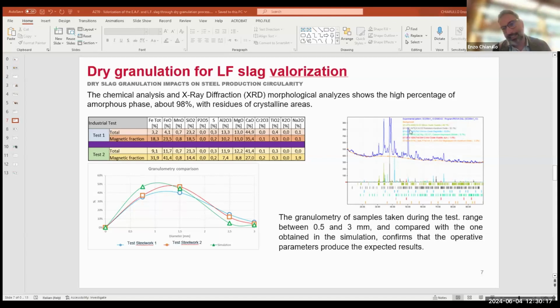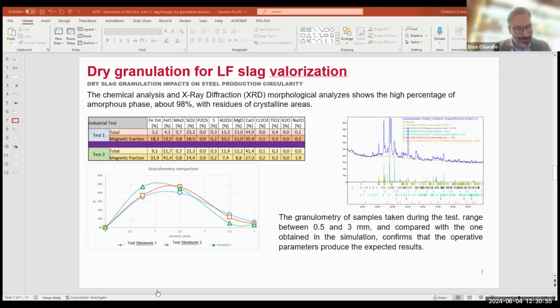Even we can obtain more, let me say, glassy texture. This is because of the amount of silica oxide available in the slag. The granulometry is changing between 0.5 and 3 millimeter, as expected as we calculated. To the relevant technology, or the technology that we are developing.